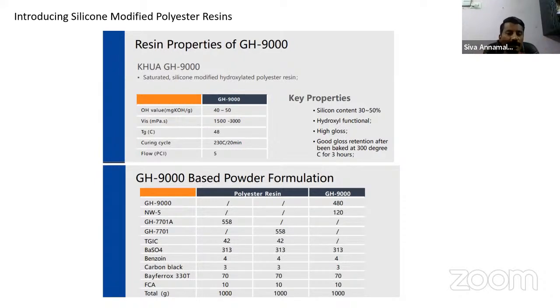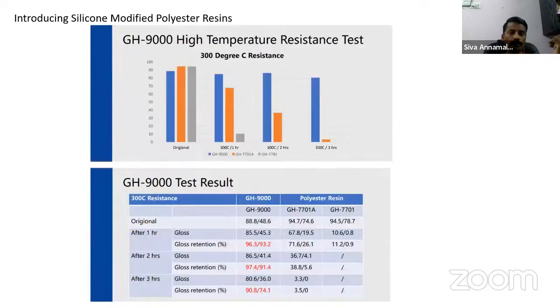So in this slide, you are able to see two polyester resins we compared. One is silicone modified polyester. Another one is normal high viscous polyester, which is currently used. This is a performance test we do at 300 degrees Celsius on both grades. We never take silicone resin for comparisons. We take only the polyester resin for comparison, because silicone and polyester are different chemistry. So that's why we do not take silicone for the comparison studies.